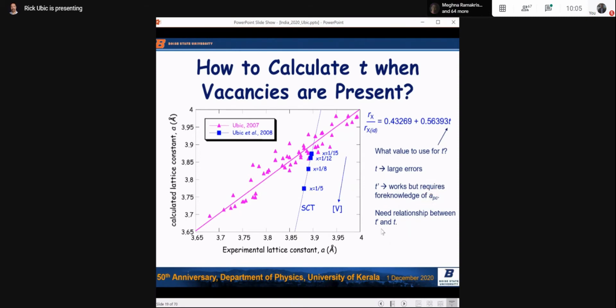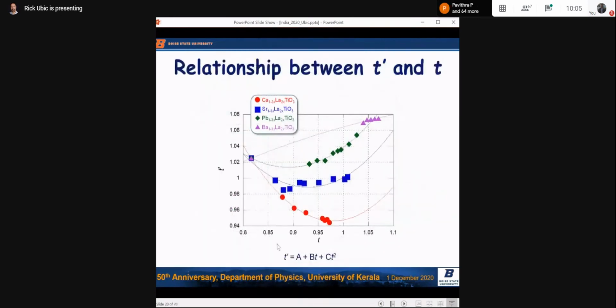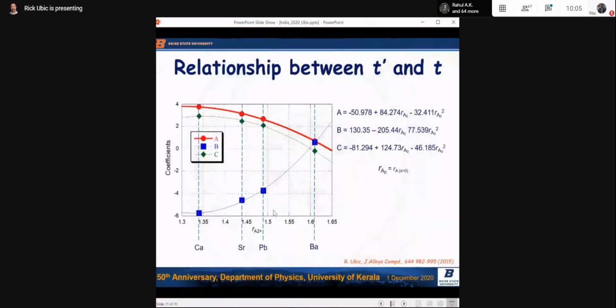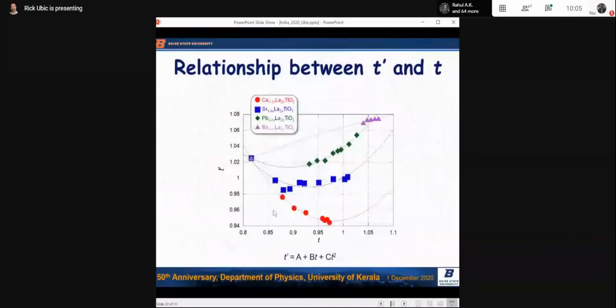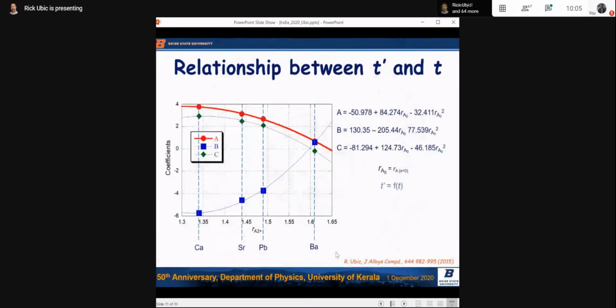So what we need is a relationship for T prime and T. We need to relate T prime to T without knowing lattice constant first. So we've got these curves. They look similar, and they are similar. They're all quadratic. It's on the slide. They all fit a quadratic form. T prime is a quadratic as a function of T, the Goldschmidt tolerance factor. So what we need to do is get a fit for the ABC coefficients.